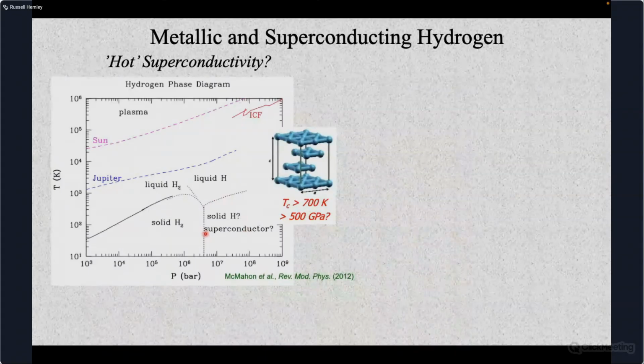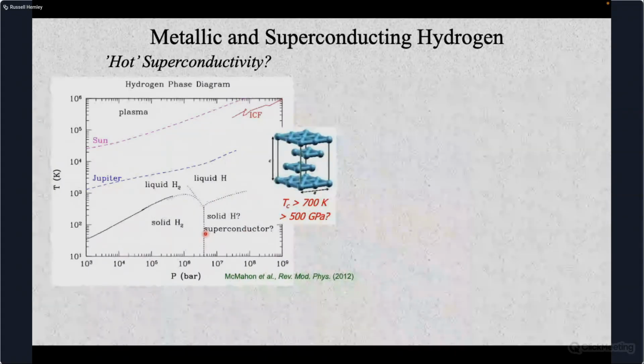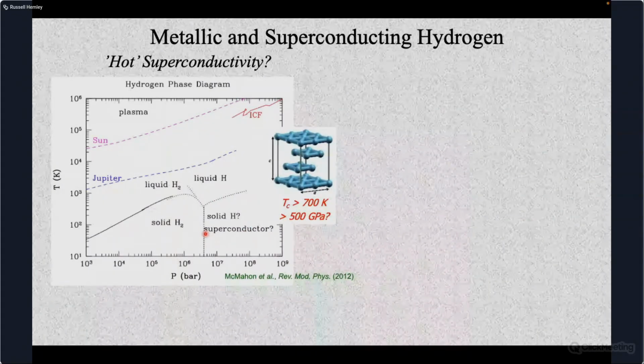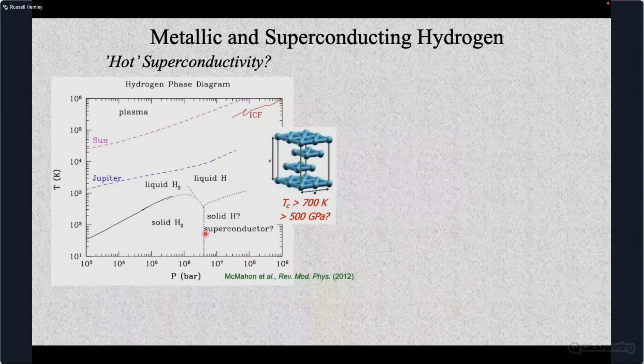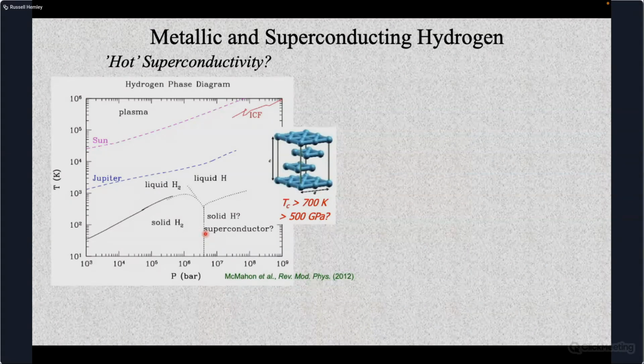And then we have this regime at very high pressure, above something like 400 to 500 GPa, where you have this hypothetical solid phase that could be a very high temperature superconductor in the solid state. There are some glimpses of this from experiments, but a lot of theoretical calculations are really converging on this regime as being what's required for the metallic or the superconducting state of hydrogen.